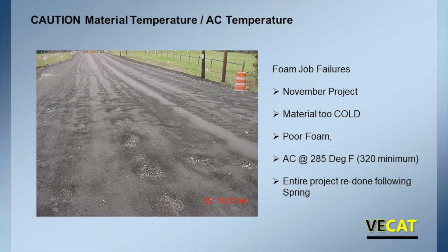When you do it wrong, that's what it looks like. So this is a project upstate New York in November. So the material was just too cold. We didn't do it, I took the picture. When the contractor added the binding agent, in this case it was foam, the foam had a poor distribution because the material was just too cold. So we had just stringers, poor strengths, potholes the first trucks would go over it. So that is how not to do it.